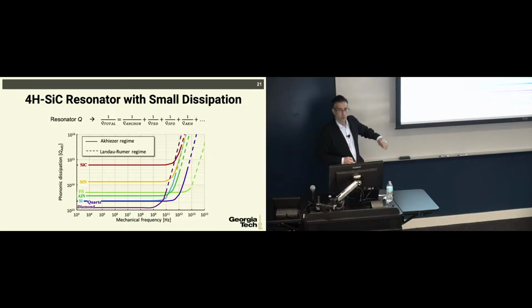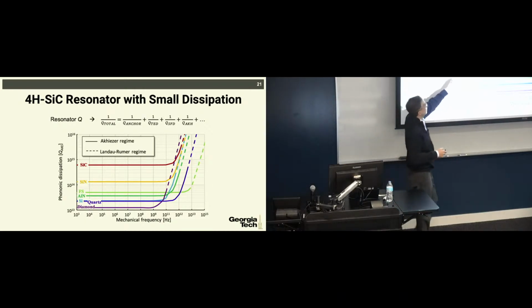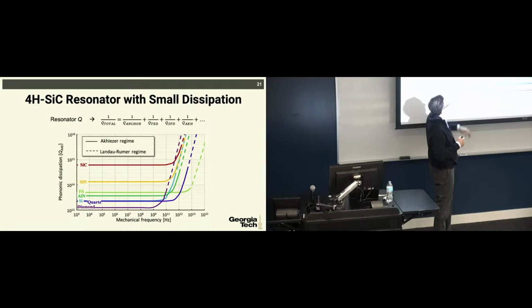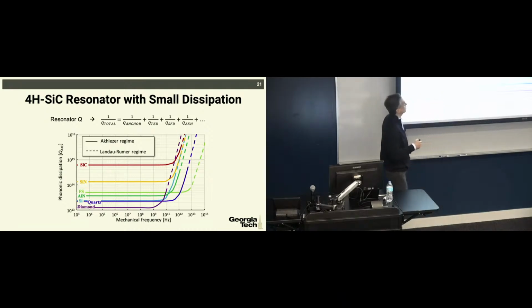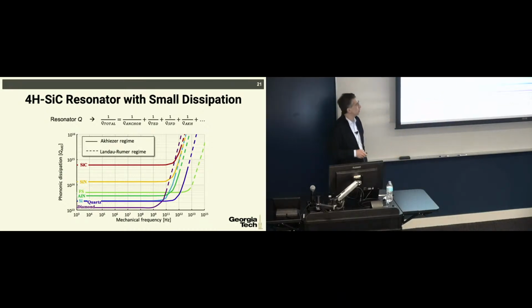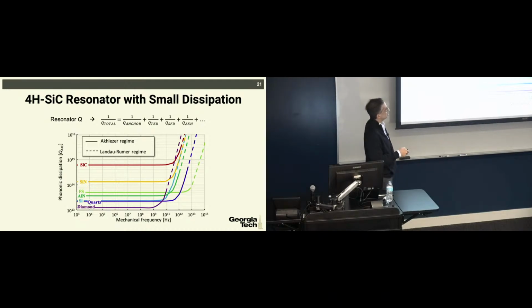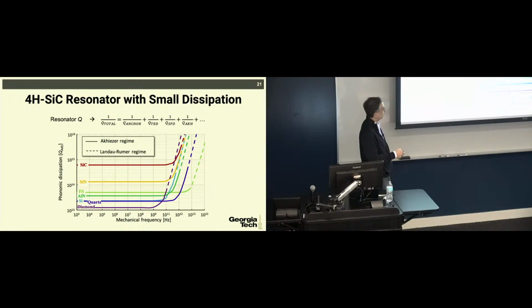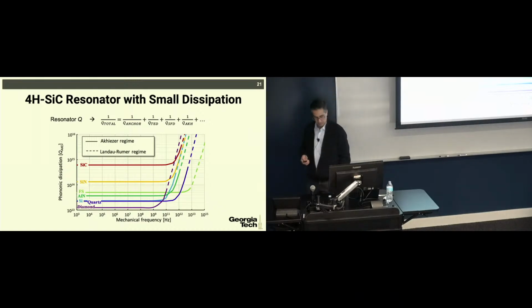And more so with the fact that, according to literature, the Q factor that you should be able to get out of a monocrystalline silicon carbide should stay much higher than any other micromachinable material that people have been working with, like silicon nitride, aluminum nitride. Silicon is here, this light blue is silicon, and you see it's near quartz. So we were really intrigued to see what is the highest Q factor we can measure.